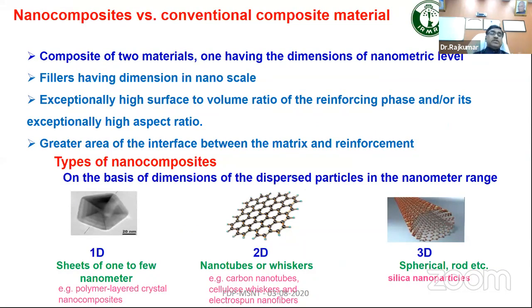So polymer nanocomposites, again, on the basis of dimensions, at least one dimension should be in nanometer, and it could be one dimensional, two dimensional or three dimensional. Fillers having dimension in nanoscale, with exceptionally high surface to volume ratio, will give you a reinforcement phase, and an exceptionally high aspect ratio. The reinforcement is mainly based on its interaction with the surface activity and because of the high surface area. And here the point is that a very small doping, or you can call it dose, gives excellent reinforcement.